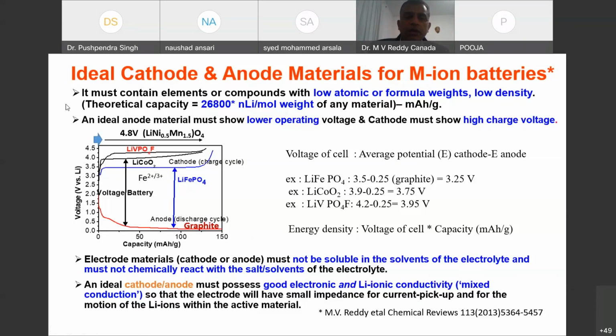And the anode should have, for example, a lower discharge potential, and the cathode should have a higher charge potential and high capacity. The voltage, again, repeating, the voltage in the cell is nothing but the average potential of the charge minus discharge. Depending on this, for example, you can see iron phosphate, cobalt, comparing all three together, the top one has slightly higher energy density because the voltage is also higher, and capacity accordingly.